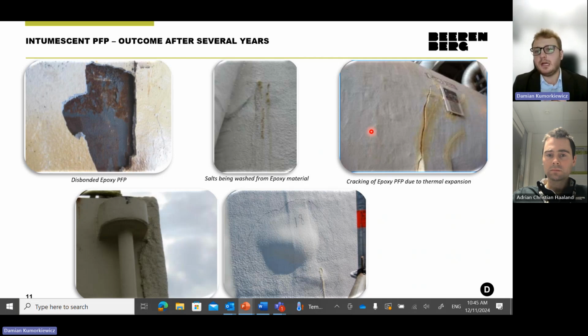However, we also see in the inspection reports that we receive from the end users that, due to some reasons, this intumescent epoxy PFP has failed. And here you have examples of disbonded epoxy PFP being washed away, cracking of epoxy PFP due to thermal expansion, poor detailing at interfaces, and blistering.